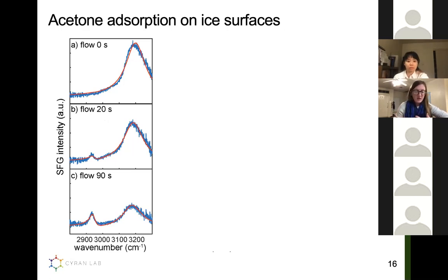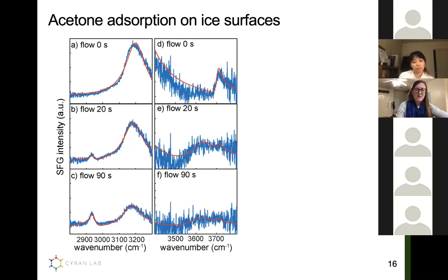Something that might catch your eye immediately is the growth of a peak at a lower frequency. This is actually coming from CH vibrations. These CH vibrations are inherent to only acetone, right? Water has no CH vibrations. So in this case, I could see specifically the acetone absorbing onto the ice surface by monitoring the CH peak here at lower frequencies.